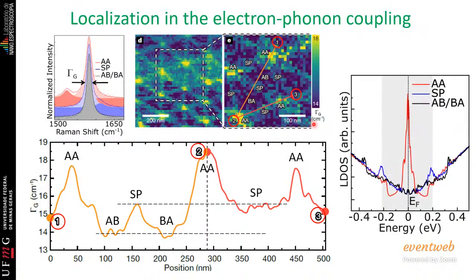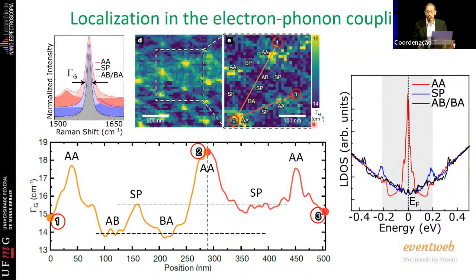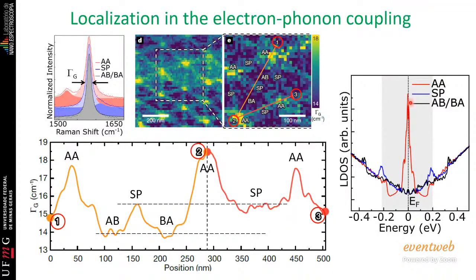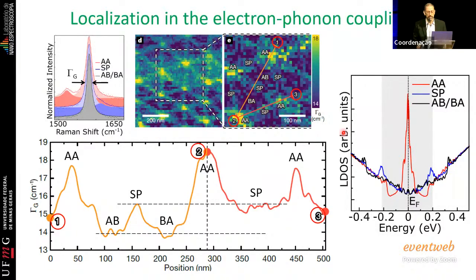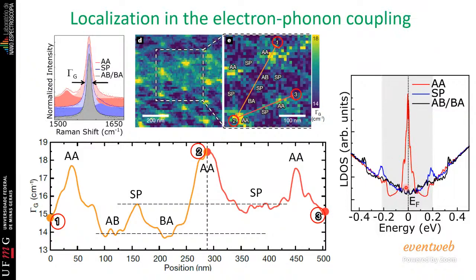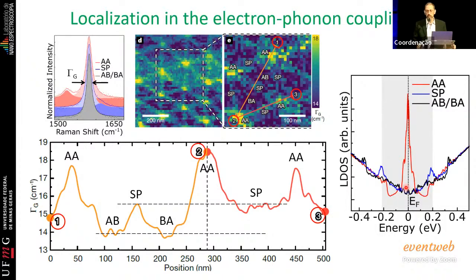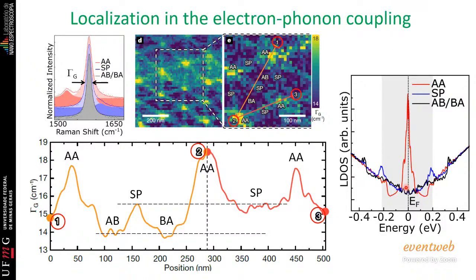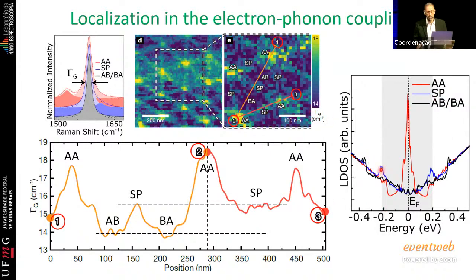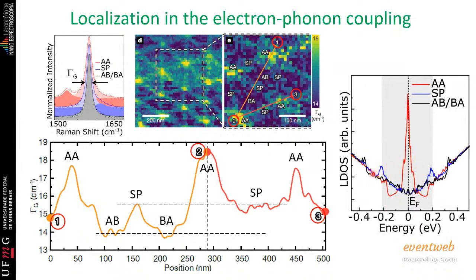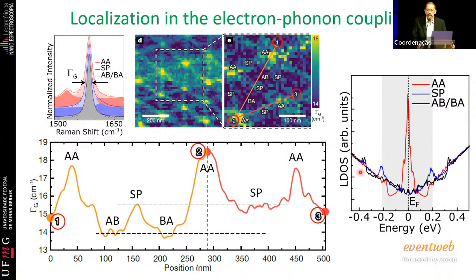And again, this can be explained by electronic density of states calculations, again atomistic, so that you can look locally. And notice that the peak that you saw that happened at the magic angle, this peak happens at the AA site. And this causes a lot of electron phonon interaction via, let's say, the decay of the phonon generating an electron hole pair. So this explains the picture. And also on the strain solitons, you have smaller peaks. The very specific aspect is that the energy of these peaks are by chance exactly the energy of the phonon.